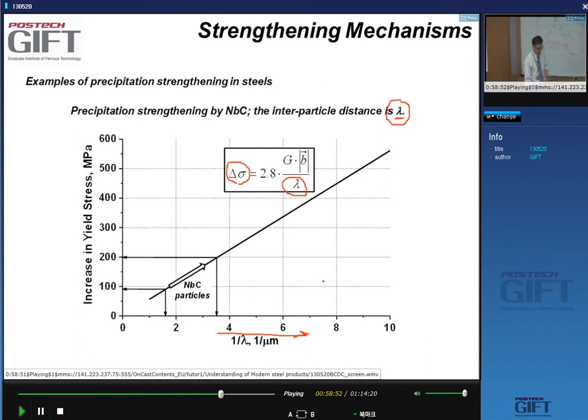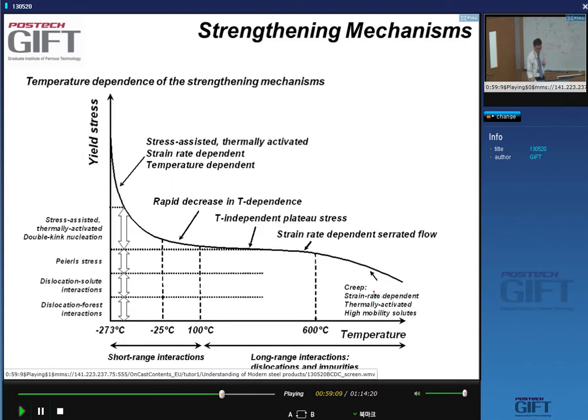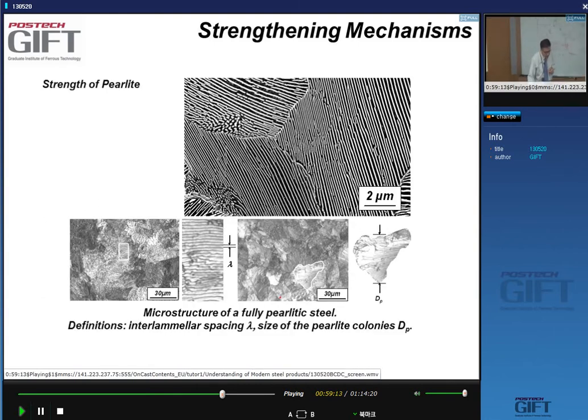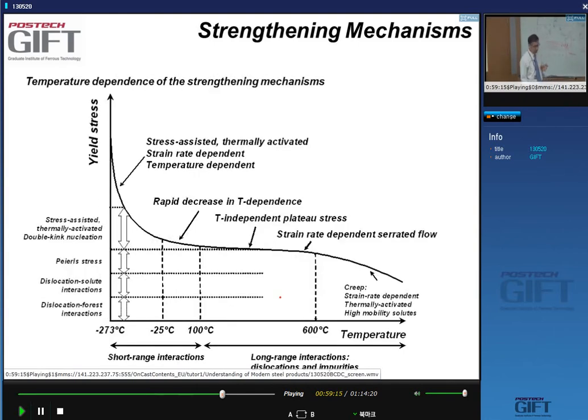But that is basically another way of saying that when you increase the volume fraction at a constant R, you will have an increase in the strength. Okay, so just a second here. Before we go into multi-phase materials, I want to say that